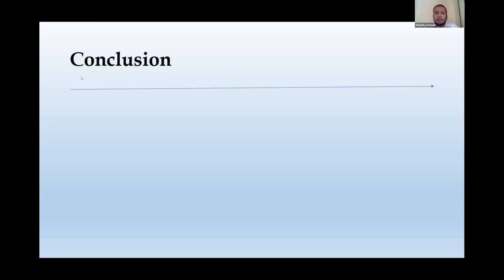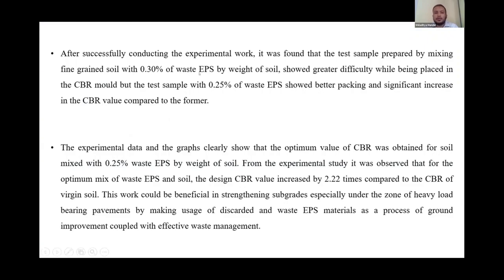The test sample prepared by mixing fine grain with 0.30% of waste EPS by weight of the soil showed greater difficulty while being placed in the CBR mold. But the test sample with 0.25% showed better packing and a significant increase as well. That is what we confirmed from our results. But 0.30, if you ask me personally, I could observe that when the rammer was falling on the sample, it was basically trying to provide an uplift kind of a thing, or probably some swelling taking place in the soil sample. So these are always the scopes of such works.